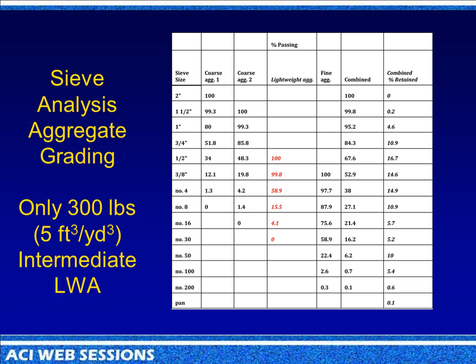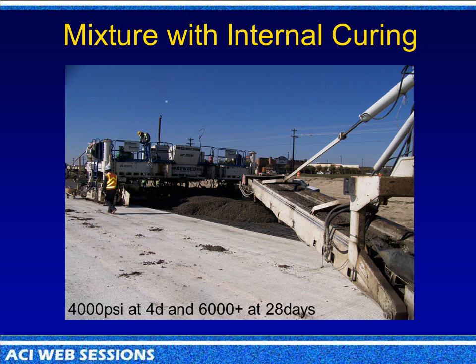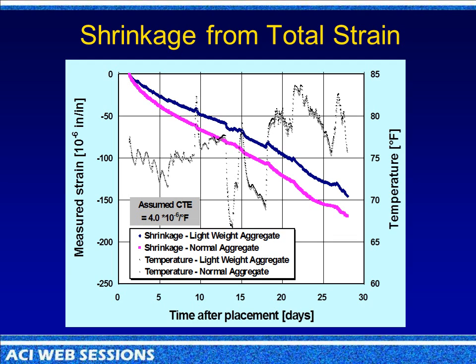And so it doesn't have to be fines. Well, we use intermediate. It's a lower grade. I mean, it's a lower sizing that we use. And here it is in real life going down. And as you can see, the shrinkage averaged about, the normal weight was the pink one, and the lightweight was the blue one. And you can see it's averaged at about 10 or 15% total less strain.